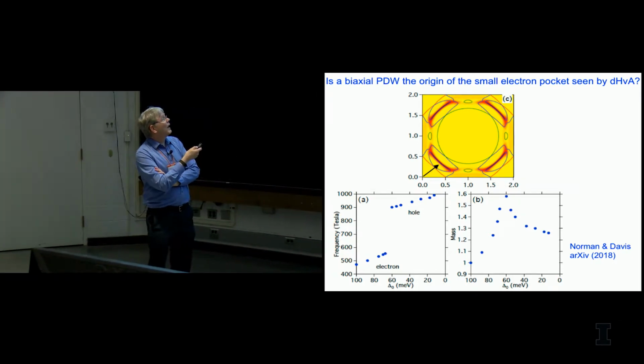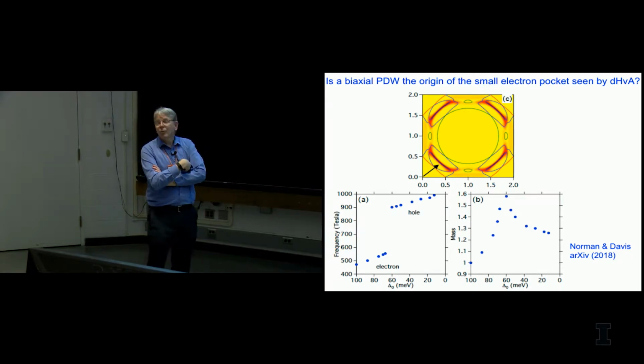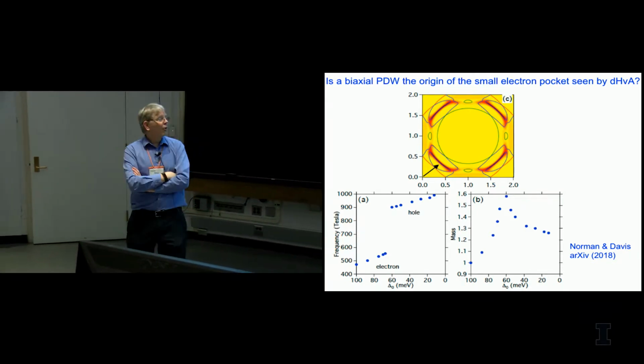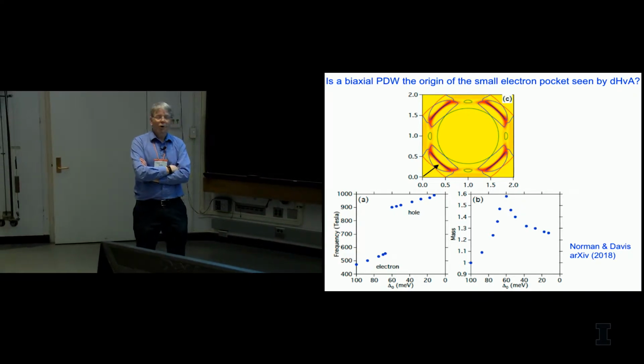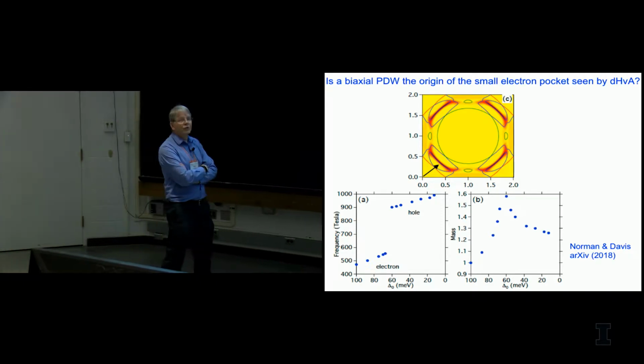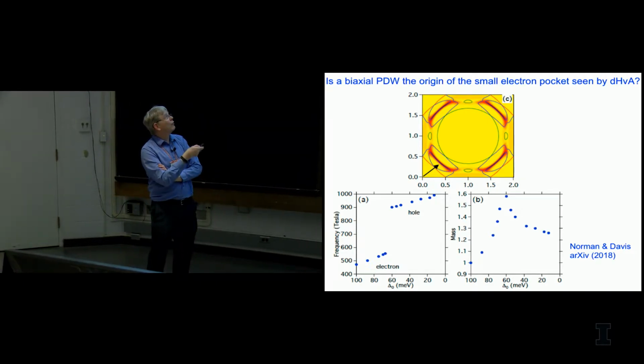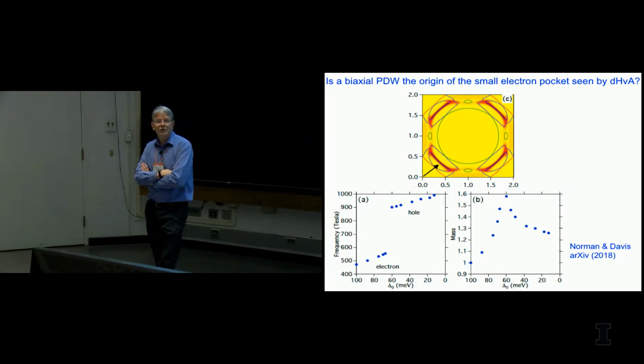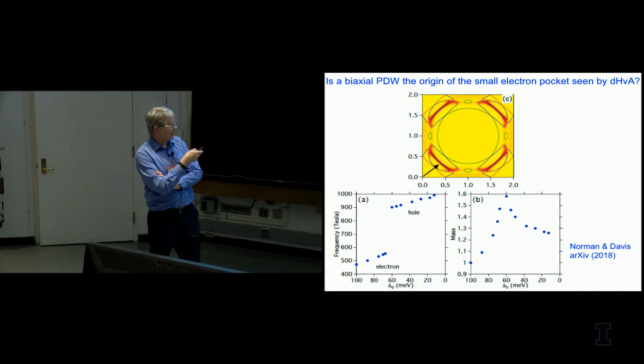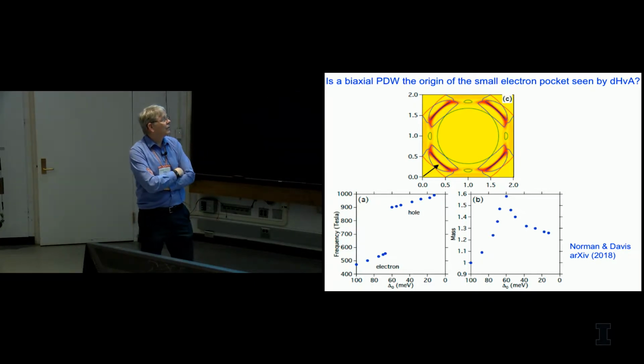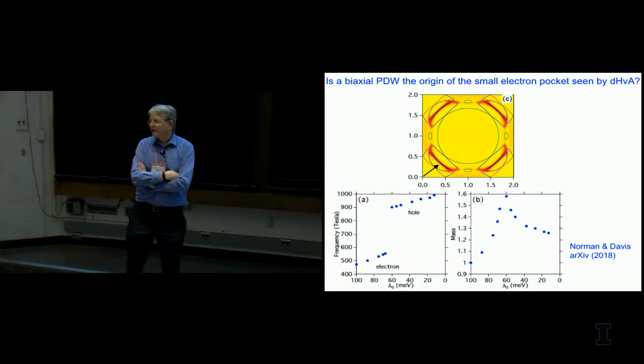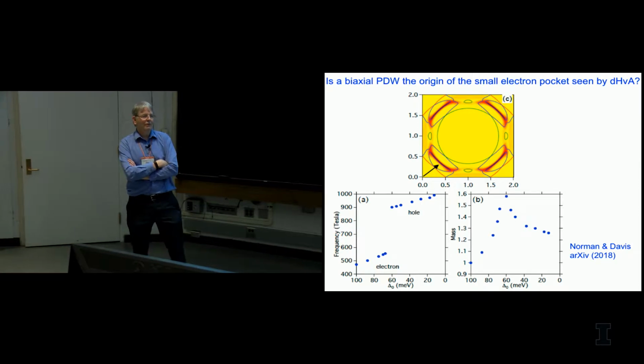So what I will say is that no one has done a full quantum mechanical treatment of this problem. I have a smart postdoc who claims that they're going to tackle this. He used to work with Alan MacDonald, so if somebody's going to do it, he's going to do it, but so far it hasn't been done. So there's a lot of controversy about whether these things will actually lead to quantum oscillations or not. But it certainly has the right behavior. It is an electron pocket, that is, if you increase the chemical potential, the area of the pocket increases. Frequencies are comparable. You have a Lifshitz transition, and that leads to an effective mass divergence, which is also seen in quantum oscillation studies. So the phenomenology looks good, but whether the theory holds up in the end remains to be seen.